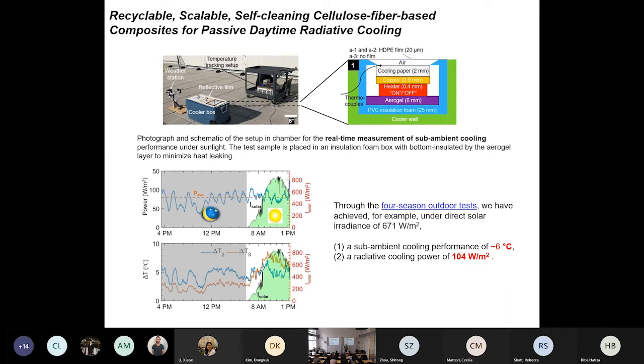So without the use of an AC system, we simply monitor the temperature inside of the house and outside the house, with our cooling paper and without, and we're able to achieve 6 degrees C cooling, and the cooling power is still high, over 100 watt per meter square. And on the top right, I just show you how the system is set up. I don't have time to go through that, but if you're interested, you can find the paper.